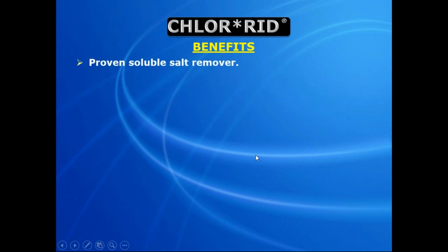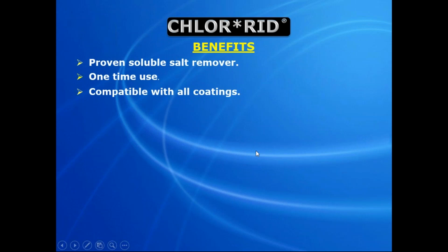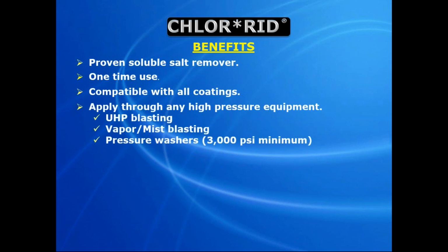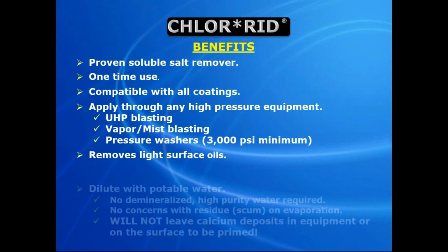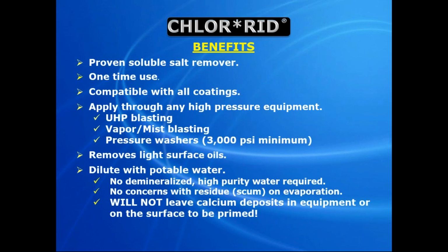The Chlorid is a proven soluble salt remover. It's one-time use only. It's compatible with all coatings. Why is it compatible with all coatings? Because like I said earlier, it's all washed away. There's no Chlorid left on the steel in any way, shape, or form. It's clean steel when it's done. And you can apply it through any high pressure equipment, even UHP blasting. It removes light surface oils that I talked about before. Light surface oils, not a whole bunch of it. And that's something you'd have to test on your own to make sure that you got it all clean.